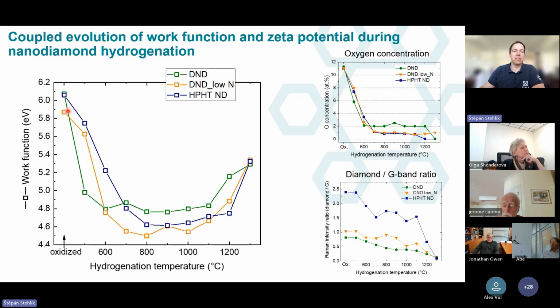So we recorded this on insufficiently hydrogenated surfaces. Here we saw some optimum, and here we saw again an increase of the work function, which is quite probably because of the graphitization at these highest temperatures. What is very important here is that it looks like DND is the most reactive, and the work function goes down already at about 500 degrees C, even though we still have about 6% of the oxygen.